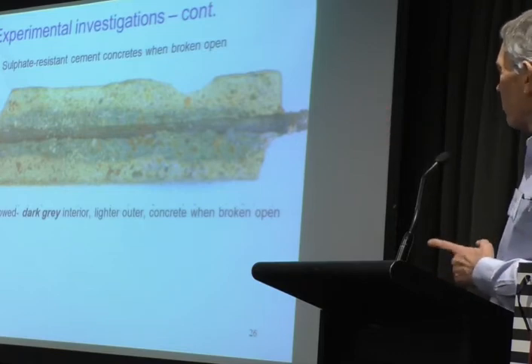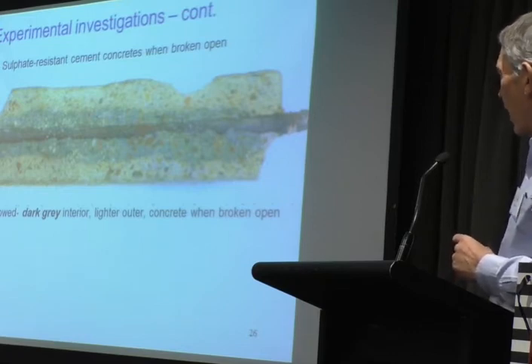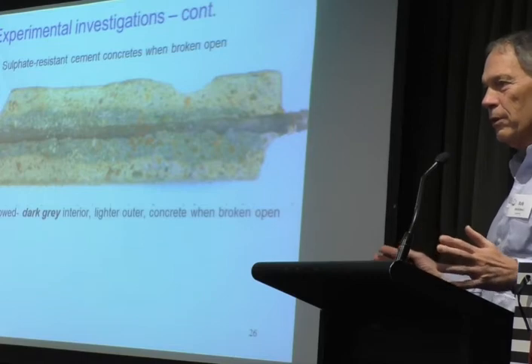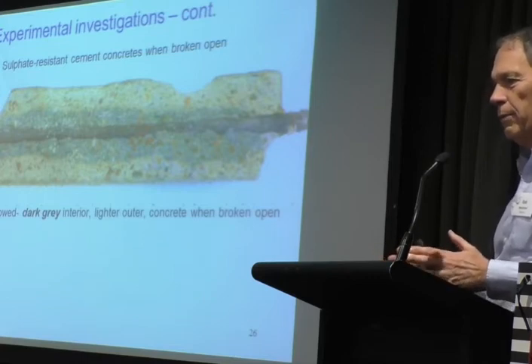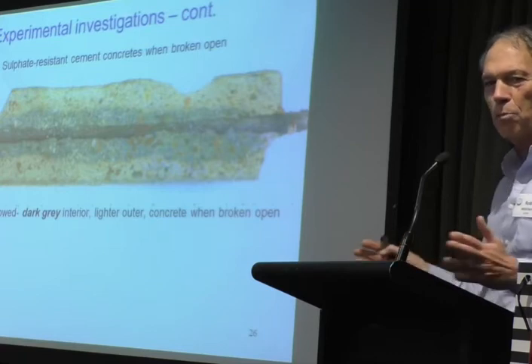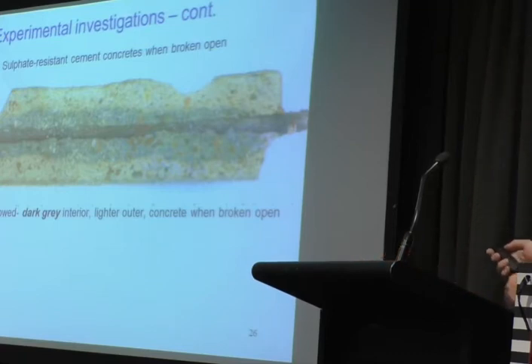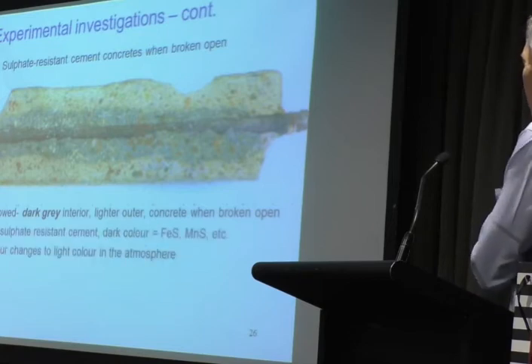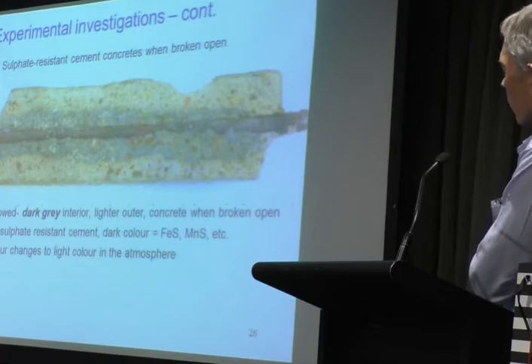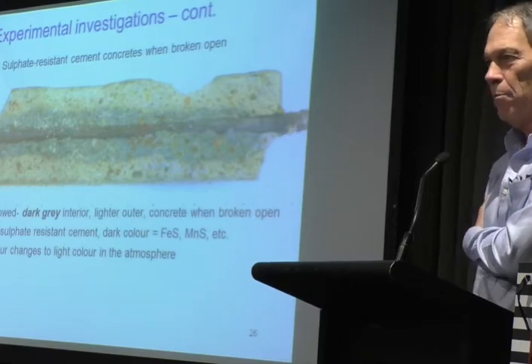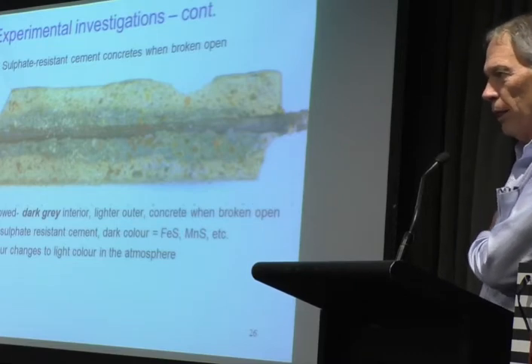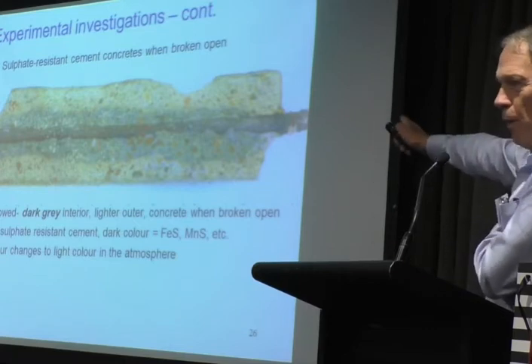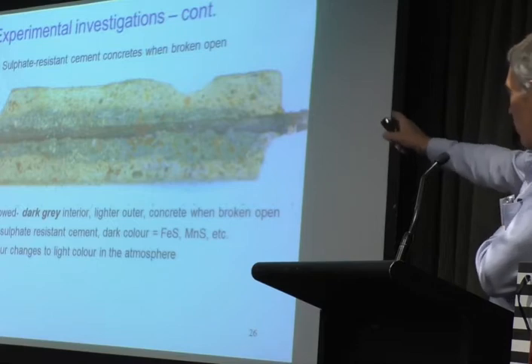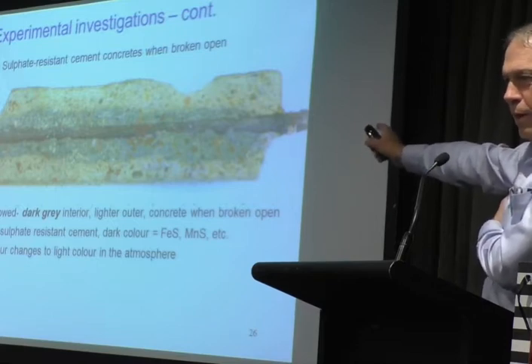And then we did discover after a little while that the dark grey material was less for the lousiest concretes, the poorest concretes. And that then said, hang on, there's something going on. There's some diffusion process going on. And, you know, it takes a while to get your head around what you're looking at. But it turns out, we eventually found that sulfate resisting cement has a dark colour because of iron sulfides and manganese sulfides in the concrete mix, and they change to a light colour on exposure to the atmosphere. And that's known, you can look that up, but these concretes hadn't been exposed to the atmosphere. Right? This is just after the thing was broken open. So you have to ask yourself, what's going on here?